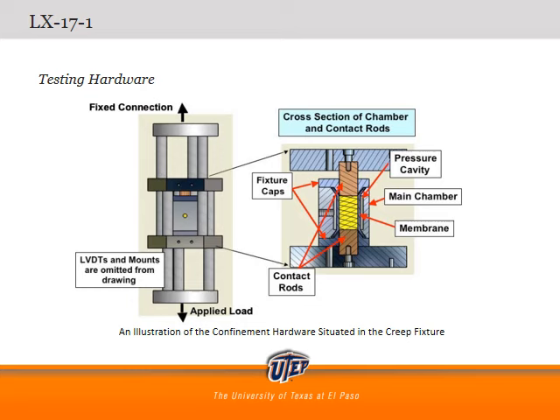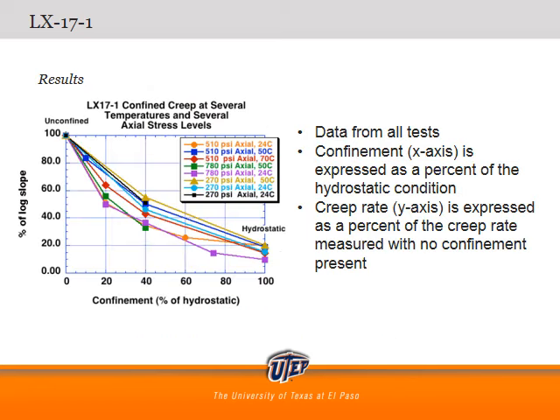And here is the figure of the testing mechanism that will apply the axial stresses and the confinement pressure to the test specimen. The graph on the left shows the data from all the test combinations, ranging from low axial pressure and low temperature to high axial pressure and high temperature. As you can see, the more the confinement pressure is increased, equaling the axial pressure, the less creep actually occurs in all cases.